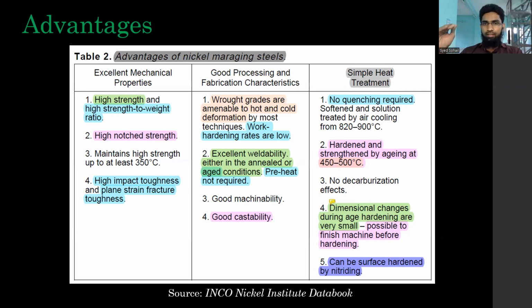In terms of high strength, it doesn't just have high tensile strength. It has high compressive strength. It has high yield strength, ultimate tensile strength, fatigue strength also. So it is high in all these aspects. And high compressive strength is desirable for the tool and die industry. Just as a side point, it maintains high strength up to at least 350 degrees Celsius, which I mentioned as property retention. Properties have to be retained at moderately high temperatures, so that retention is another advantage of this material. High impact toughness and plane strain fracture toughness. Toughness properties come into play, and I explained why they are needed in certain industries.